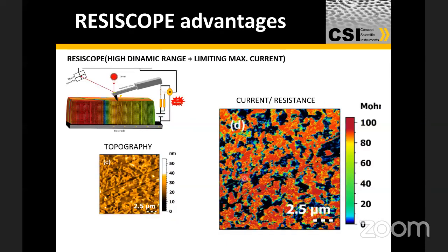And you can see the difference on the same sample with the resiscope. Once you use the resiscope, because the resiscope is able to control, in a certain sense, really the amplifier that's controlling the tip current, you come up with really being able to measure the surface itself, rather than the tip having current issues and things like that, and resulting in poor resolution. You're able to make much cleaner and much improved current measurements on this graphene oxide layer.